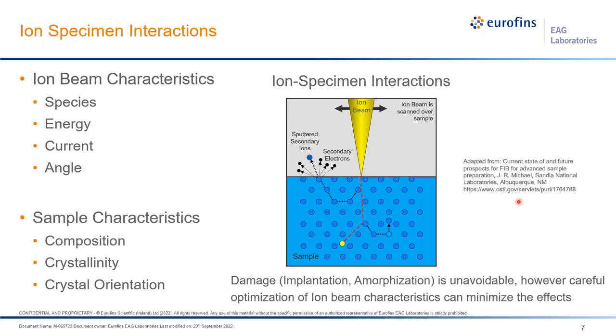So when the ion beam impinges upon a sample, a variety of things can happen. There are a series of elastic and inelastic scattering events that occur between the incident atom and the sample. You can have both implantation of incident ions into the sample, as well as displacement of sample atoms. And even in certain cases, you impart enough energy to knock atoms out of the sample, which are known as secondary ions. So we can select the characteristics of the ion beam to maximize the effects we want and to minimize the effects we don't. But there are also sample characteristics like composition, crystallinity, and crystal orientation that must also be considered as well.